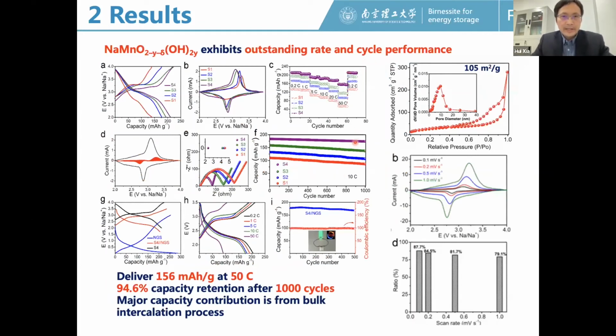Then after that, we look at the electrochemical performance. So we find that this Birnessite has a large specific capacity. For the S4 sample, the reversible specific capacity can reach above 200 milliampere hour per gram. And the S4 sample also exhibits very good rate performance and cycle performance. At a high rate of about 50 C, the electrode can still deliver 156 milliampere hour per gram. And after 1,000 cycles, this S4 electrode can still retain 94% of the capacity. And this cycle performance outperforms the previously reported O3 type or P2 type sodium manganese oxide.